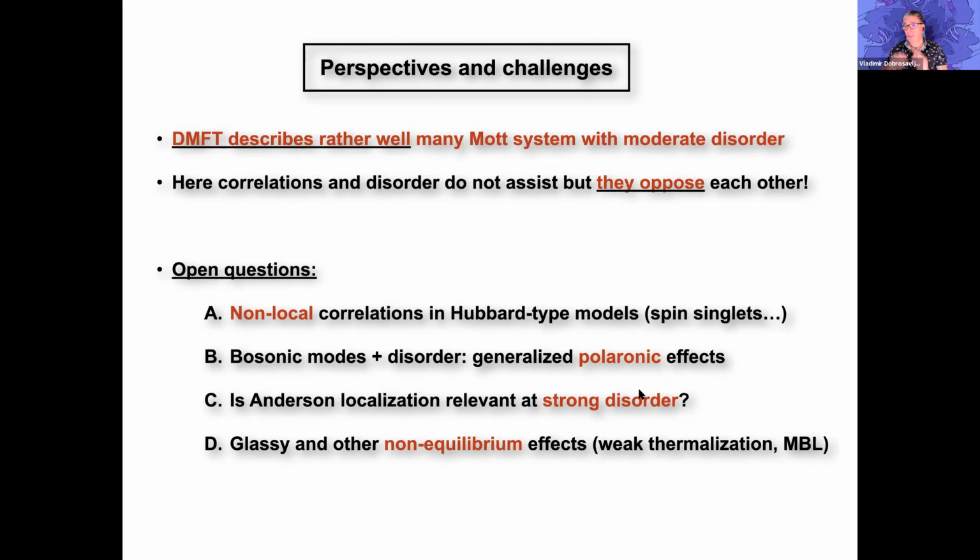Then the self-energy doesn't have only a diagonal component, but it has an off-diagonal component, sigma 1,2, renormalizing the hopping between these 2 atoms. And that can have a very profound effect. What we've discovered in our papers is that if you have a coexistence region, for example, the off-diagonal self-energy, which is beyond the local self-energy, in the metallic solution is very small, but in the insulator it becomes very large. It renormalizes at 0 frequency the hopping. So when the hopping becomes very large in a dimer, you form bonding and anti-bonding states, and that helps open a gap.